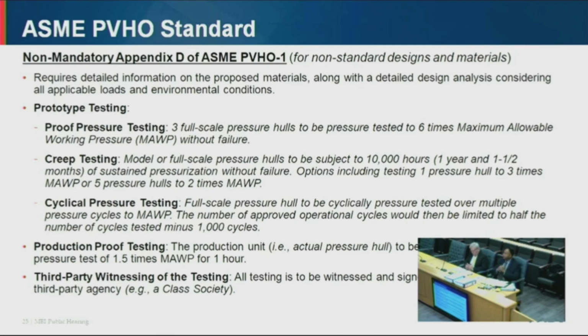After the creep testing, the next thing is cyclical pressure testing. This is basically a fatigue test. So you take a full-scale pressure hull, and then you will cyclically pressure test the hull for a number of pressure cycles. The approved operational pressure cycles will basically be half the number of cycles you tested minus 1,000 cycles. Okay, so that is how you get the fatigue life of the hull.